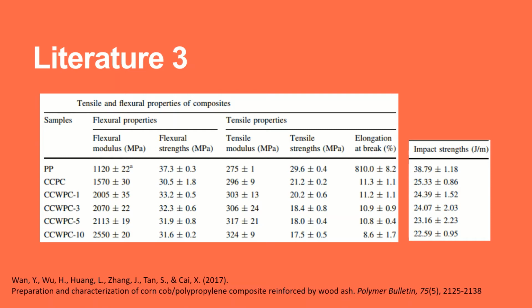Thus, the decrease of flexural strength. Third, the tensile modulus of the corn cob flour wood ash polypropylene composite increased with increasing the load of wood ash. But the incorporation of corn cob flour and wood ash into the composite resulted in the decrease of tensile strength. Fourth, the addition of corn cob flour and the loading of wood ash adversely affected the elongation at break